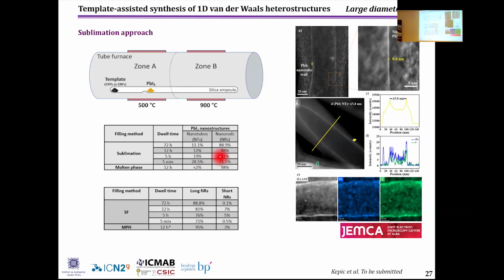Apparently, there was no trend between the time of treatment and the formation of nanorods, but at 72 hours, almost no short nanorods were observed. So this suggests that during the treatment, we sometimes sinterize the crystals which are inside the material.